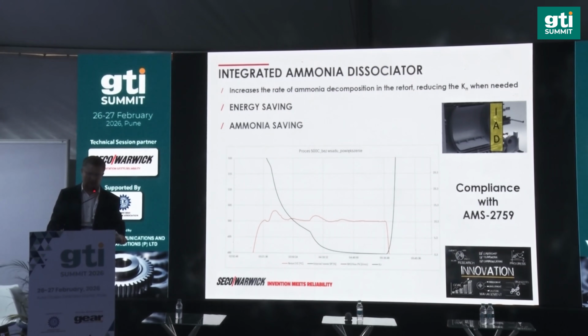It's an internal solution which is placed into the retort and increases the dissociation of the ammonia only when it's needed. Usually it is needed only between the first and second step, for example to remove an unnecessary white layer, because in some applications the white layer is not needed or needs to be very thin.